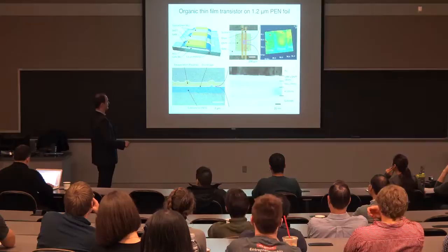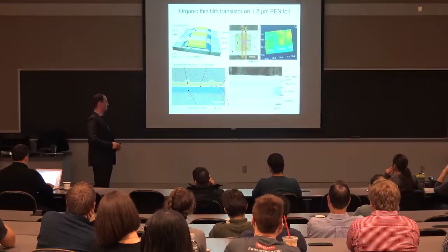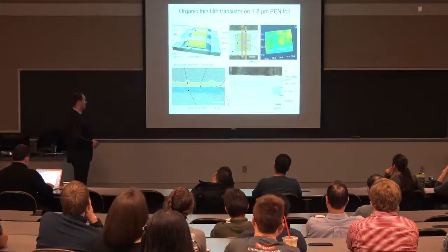It's aluminum oxide, and that's pretty much chemically grown. And the advantage of this metal is you can actually form a dense oxide irrespective of the roughness of the substrate. And you can scale it just by the anodization voltage. So this is very precise metal. A very dense oxide on an even extremely rough substrate. So this is again the illustration that we encapsulate this in a neutral mechanical plane.